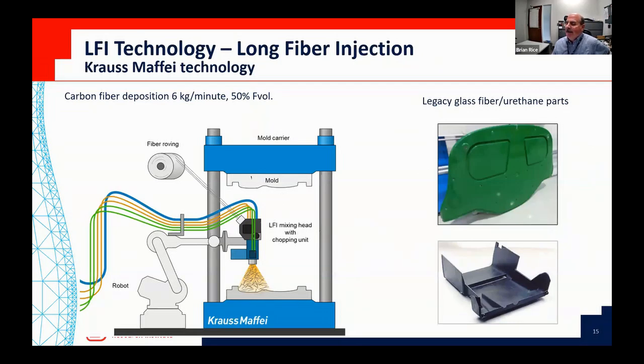Now shifting gears a little bit from continuous fiber composites, we acquired from Krauss-Maffei something called long fiber injection, which is essentially a robotic wet spray up of chopped, what used to be, presently is, glass fiber with a urethane resin. So for example, John Deere tractors utilize a lot of these parts or this process to make parts where you can actually do in-mold coatings and that type of thing. Our project with the Air Force and Krauss-Maffei and Lockheed is, say, okay, we want a robotic process that's very rapid, essentially zero scrap, but we need more aerospace properties, right?